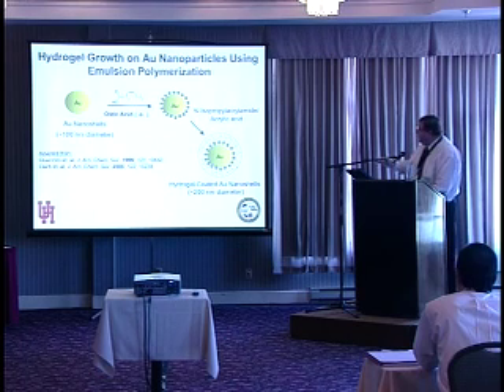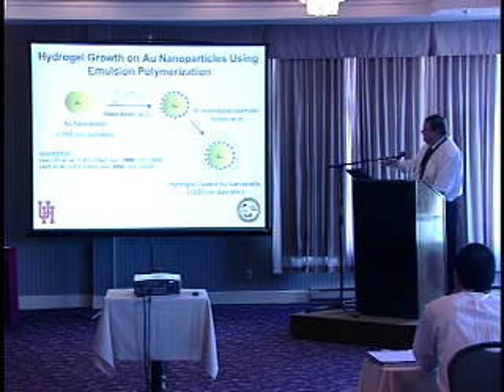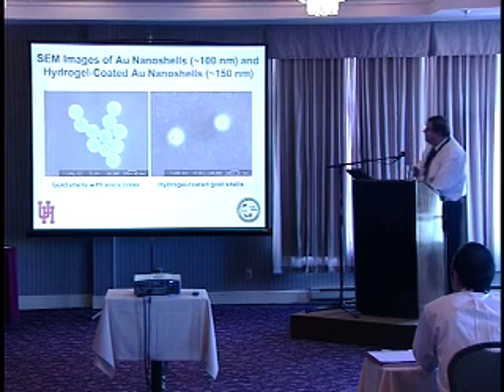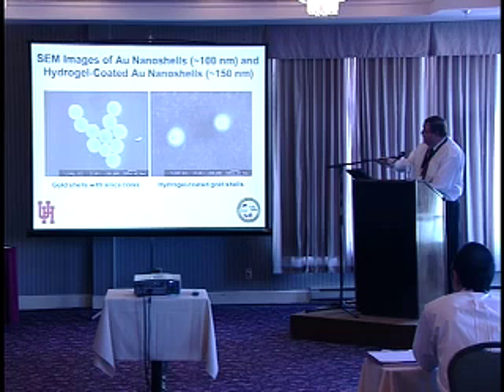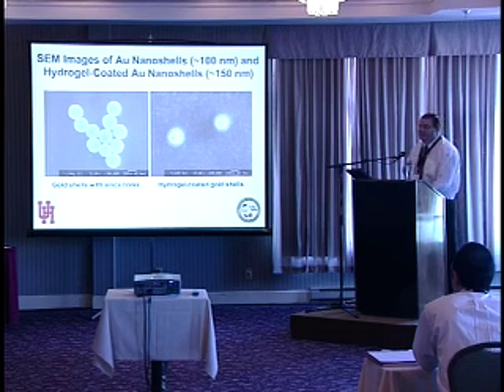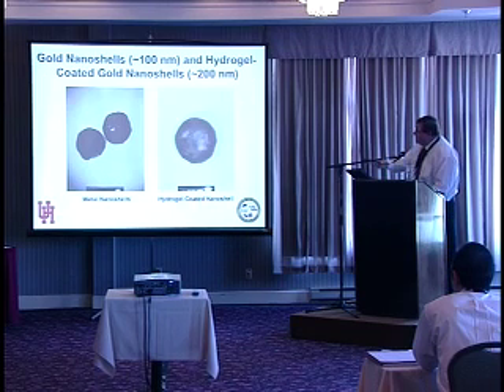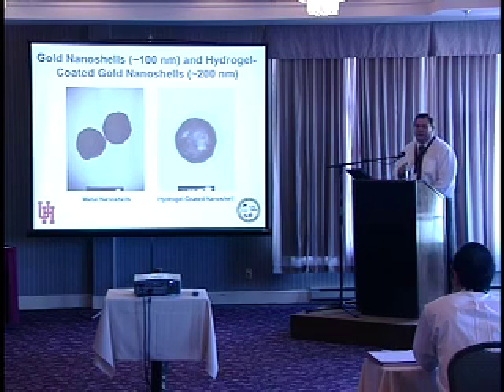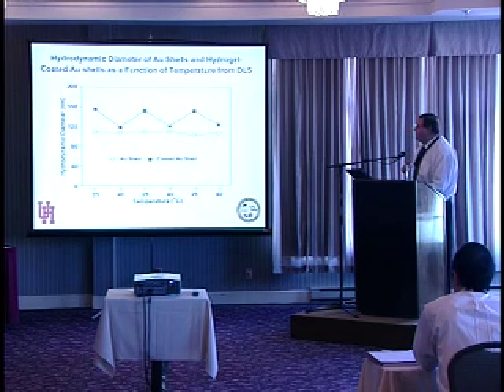Can we grow polymers on the outside of these nanoshell particles? We use the same process that we were doing with the simple gold nanoparticles. Take them, treat them with oleic acid and our monomers, and grow the shell. Here are some SEM images of the bare gold particles, and these are the hydrogel-coated particles, which again suggests that the process is working for the nanoshells. Here are TEM images, bare and then hydrogel-coated, that confirm further that we're able to do this sort of process.